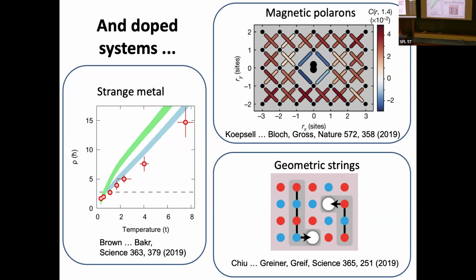Okay, so this is bulk transport. This is the kind of thing you could do in condensed matter physics. But the advantage of these microscopes is you could also do microscopics. And these are experiments from Marcus Greiner's group at Harvard and from Immanuel Bloch's group in Munich, where they actually start from an antiferromagnet at half filling and inject a hole into it. And then they can go microscopically track what the hole is doing in the system. So this is basically a microscopic version of these experiments, essentially in the limit of zero doping, just one hole doping.